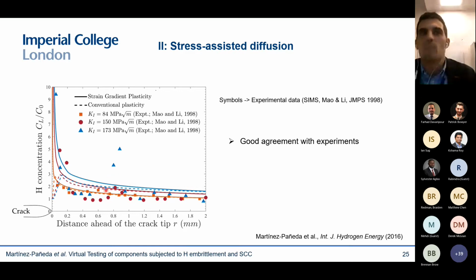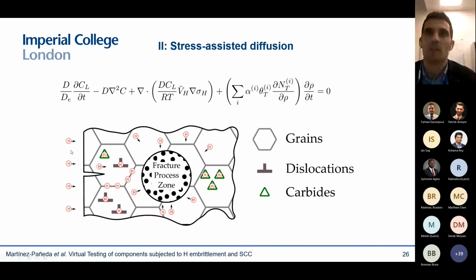One is that the concentration of hydrogen increases with the remote load. And the other one is that the concentration of hydrogen increases as you approach the crack tip. So this looks promising. And as you say, the equation that I was showing before, that extended version of Fick's law, is the simplest one can use to model hydrogen diffusion.